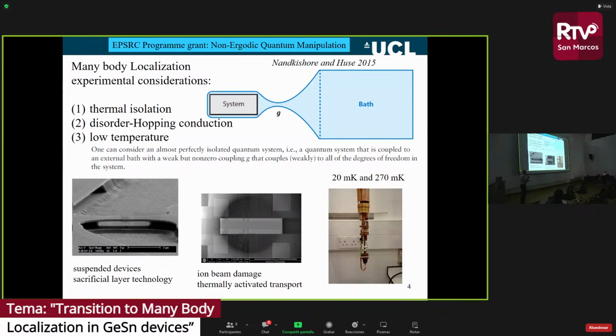Now, not in germanium tin, but this is actually in gallium arsenide. We can do that in gallium arsenide. We're trying to do that in germanium tin. And what we do here is we nominally take away the way that the lattice can vibrate. We can't take away all the phonon modes. There is a zero energy phonon mode. We can take away most of the phonon modes.